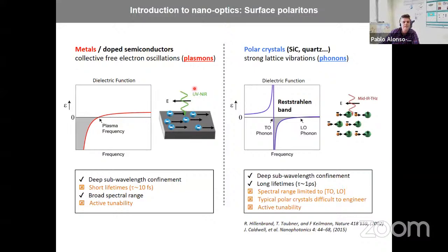But now I want to call your attention to another kind of polaritons, which are phonon polaritons. The physics is the same: conditions for Maxwell equations, these surface waves, etc. But in this case, instead of having a negative permittivity because of the free carriers in the metal, we have a negative permittivity in the material because of lattice vibrations. These are phonons. It is well known that polar crystals have a negative permittivity between the TO and LO phonons, and this happens in the infrared spectral range. It's called the Reststrahlen band, and it's because, in the same way as before, when the infrared light comes to the material, because it's a polar crystal and one atom is more electronegatively charged than the other, there is a tiny dipole next to these phonons that can react also, screening out the incident field. So instead of this collective movement of electrons, now we have this collective movement of the lattice that also screens out the incident field.